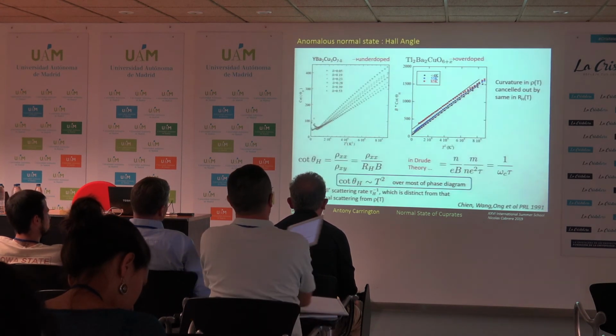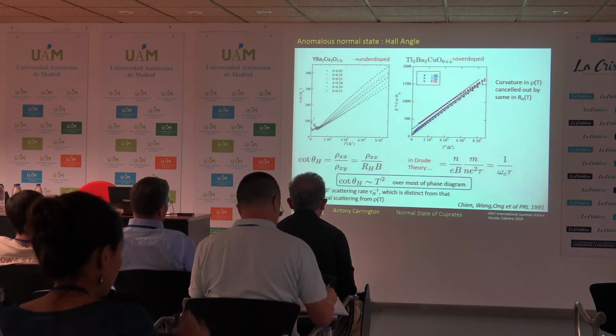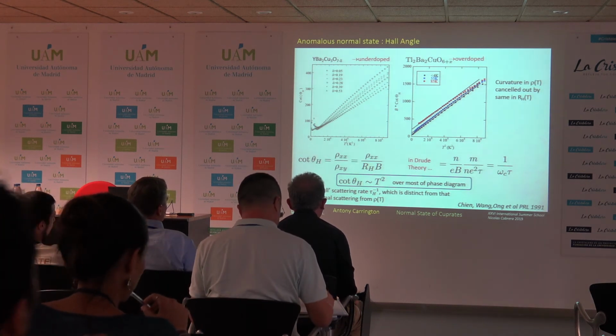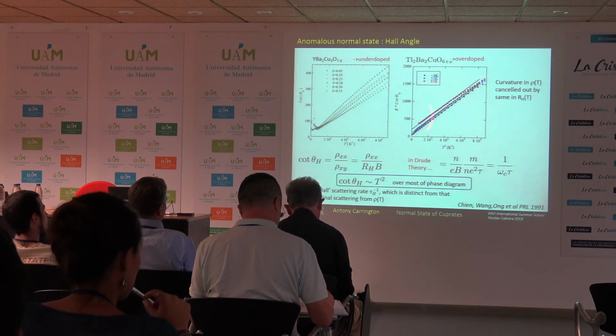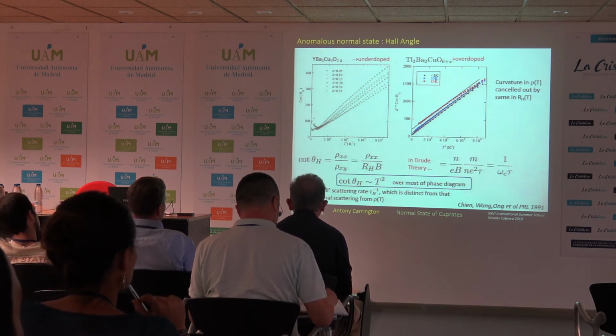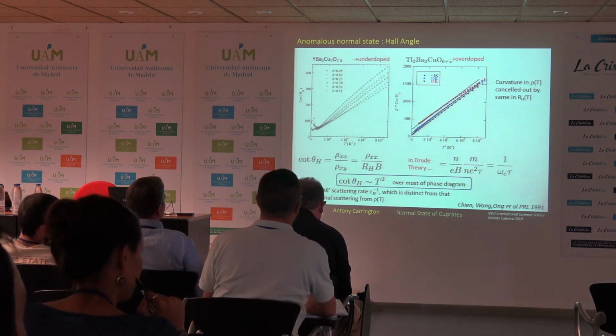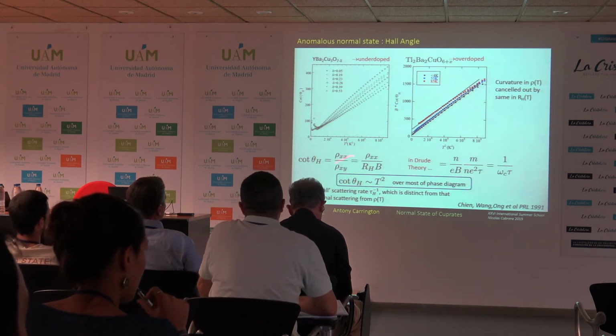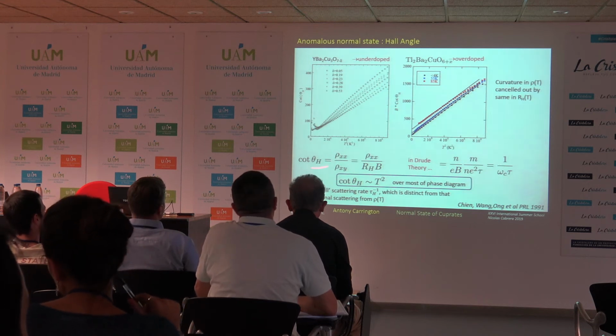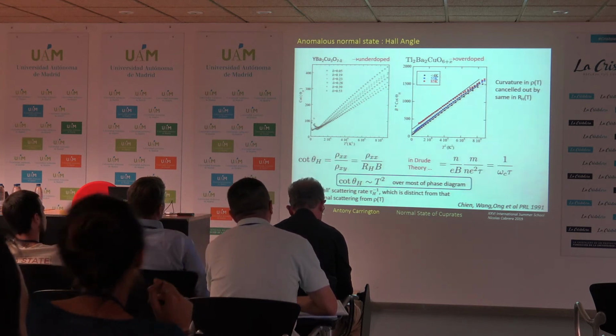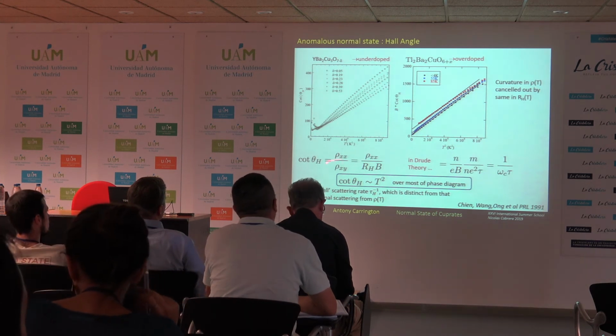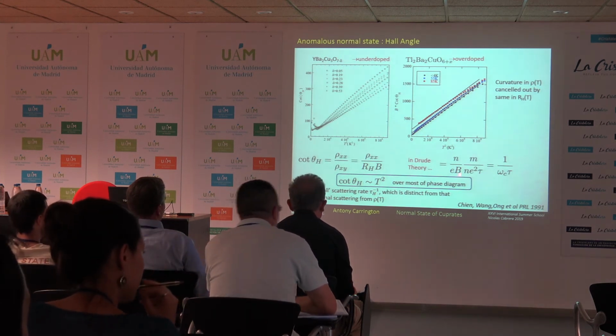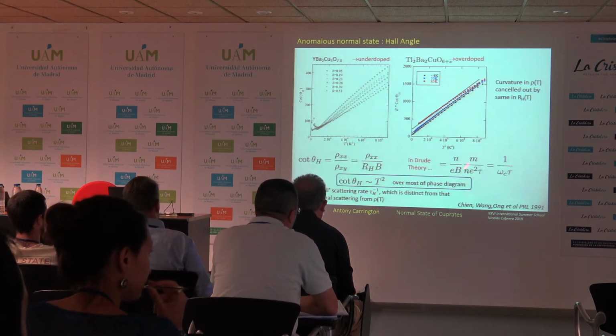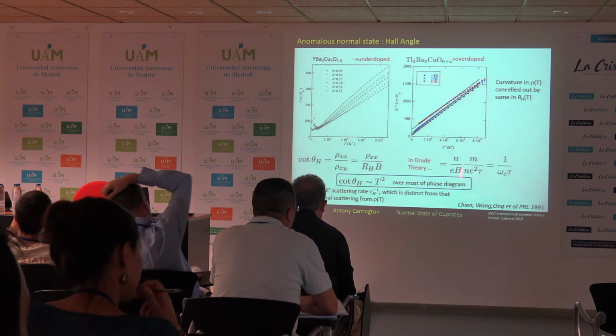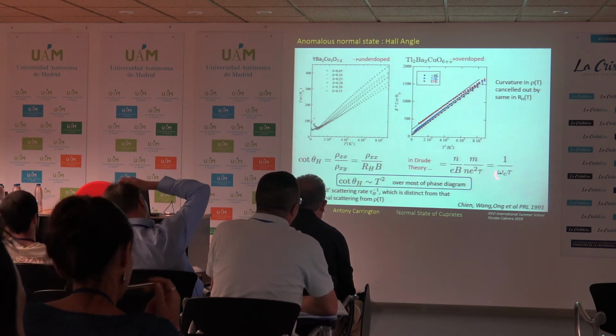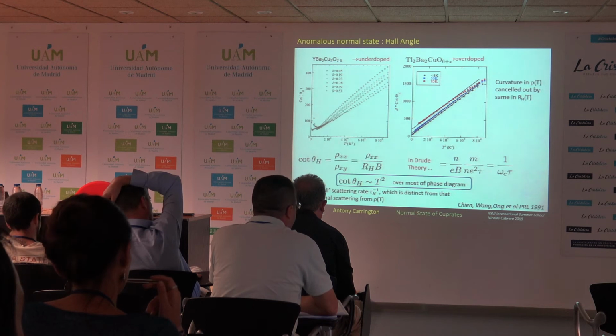But it was pointed out actually by Anderson originally that something that does seem to be more conserved over the whole of the phase diagram, in fact he didn't know that when he made the suggestion, but it was subsequently proved to be true, is the ratio of the resistivity to the Hall coefficient, so the cotangent of the Hall angle. So in Drude theory, you would just take the ratio of the resistivity to the Hall coefficient, you'd end up with a quantity which is essentially 1 over omega c tau.